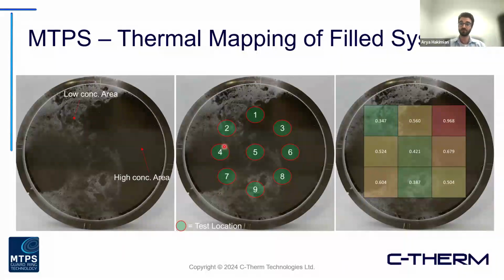And what this can really do is thermally map your sample and understand the consistency, or in this example, the lack thereof, of that thermal conductivity performance. So you can see here, the top left quadrant, based on this test location, coming in at about 0.35 watts per meter Kelvin. And we can see that it's fairly low based on the fact that there's very minimal filler present in that test area. Whereas if you move over to spot number 3 here, we get a value almost 3 times higher.